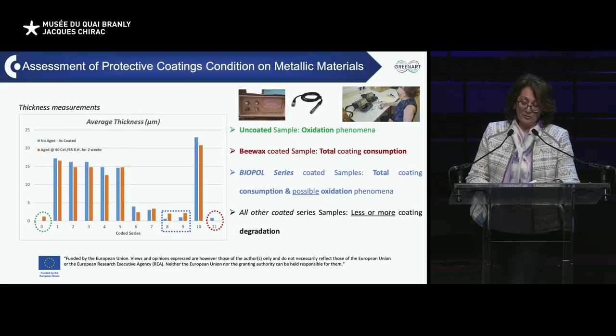The general rule and majority of degradation phenomena on organic coatings tend to decrease and eliminate their thickness. Our thickness measurements are based on electric resistance of a non-conductive coating on a conductive metallic sample. Either organic coatings or oxidation product films are commonly non-conductive materials, and in this way, you can estimate their thickness. In this respect, thickness measurement can assess, in a second order, after optical inspection, the condition of coatings.